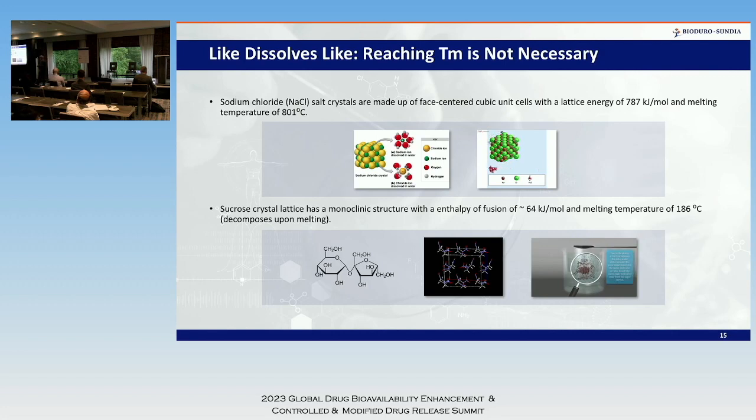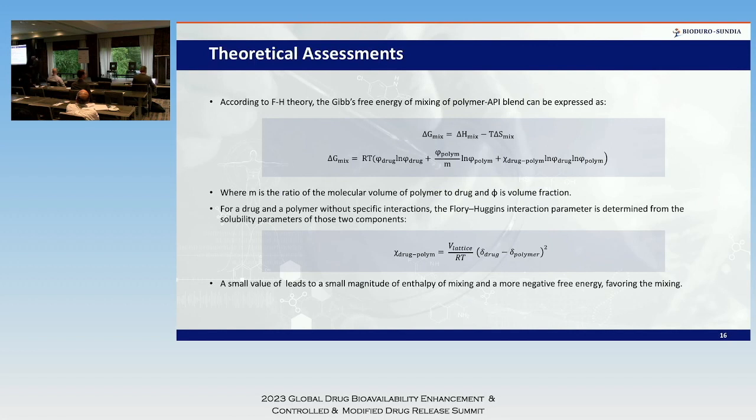You get ibuprofen and you put it with Eudragit E at room temperature, come back in a month, it's going to be one phase. Because actually solids can dissolve into each other, it's just a matter of time when that dissolution is going to happen. So we need to not only look at what polymers have been utilized for amorphization of other drugs. Let's say the Kaletra example comes all the time.